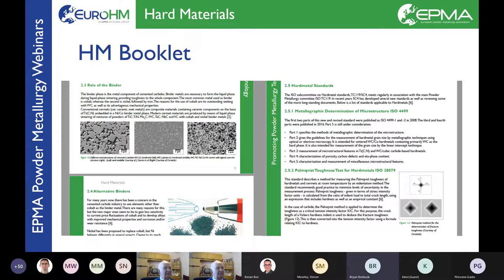So I'm going to say a few words about the binder phase, and not too specific, but just some generalities, I think, really. And then finally say a few words about standards. And clearly for hard metals, the primary one for the binder phase is to enhance the toughness of the material. We know pure tungsten carbide is reasonably tough as transition metal carbides go, but the binder adds to this toughness by absorbing energy when the material is subjected to stresses. The more binder we add, the tougher it gets. But there are other effects which I think are worth noting.